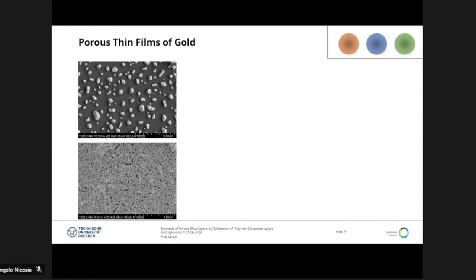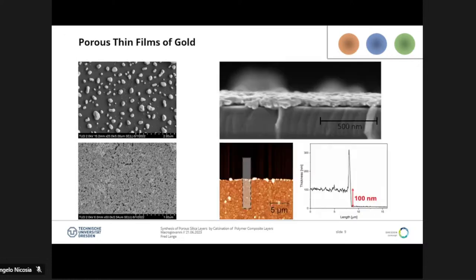But I found out that oxygen plasma treatment can also get rid of all the organic compounds, and so oxygen plasma is an alternative to using high heat for the calcination step. And this left me with homogeneous layers of gold that show a certain porosity.